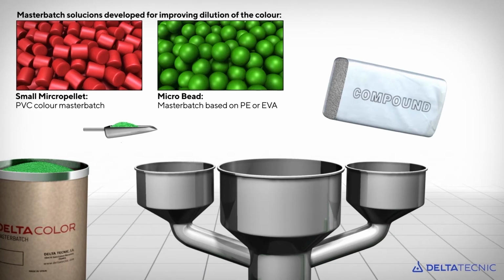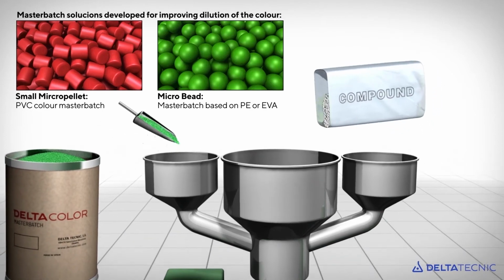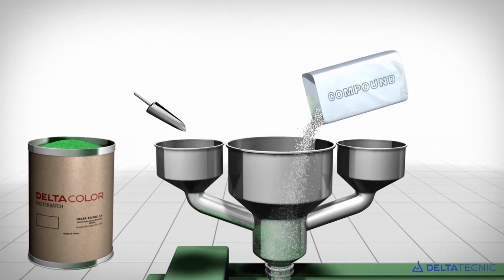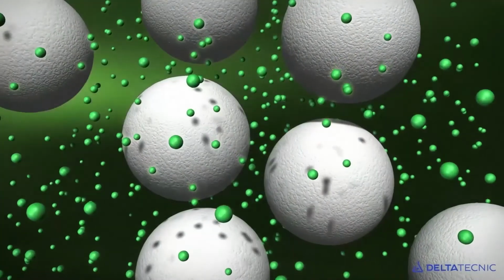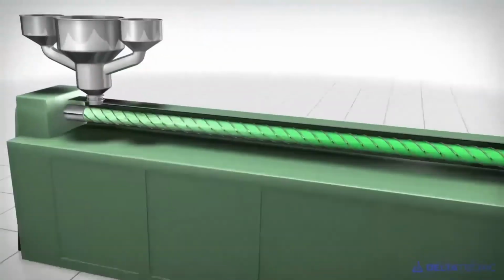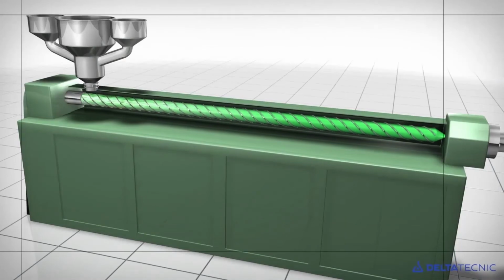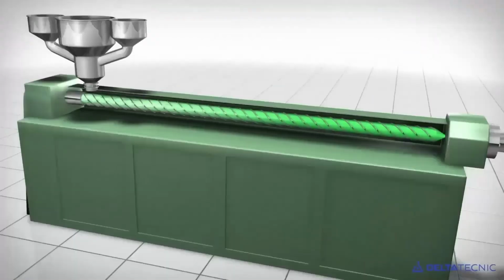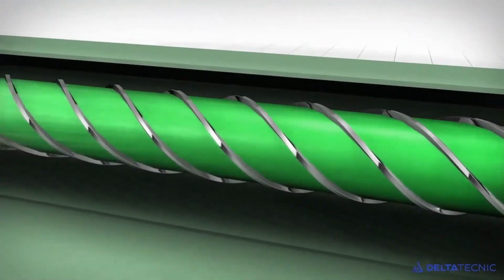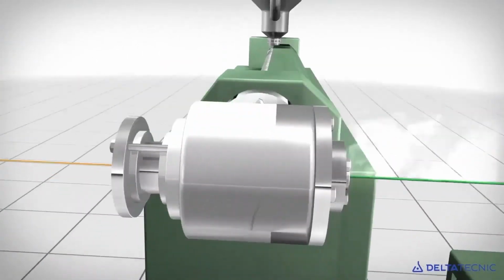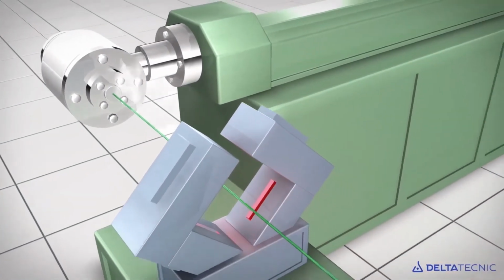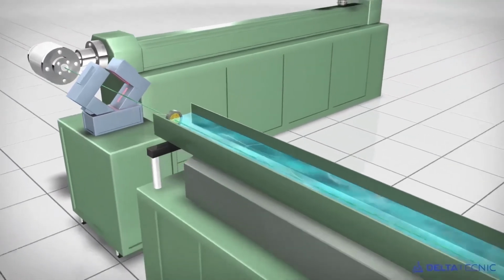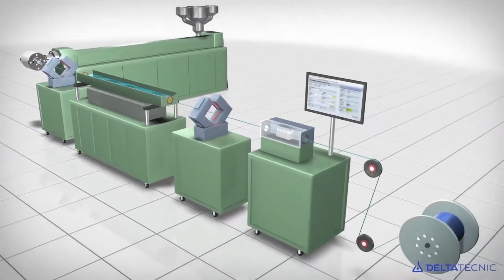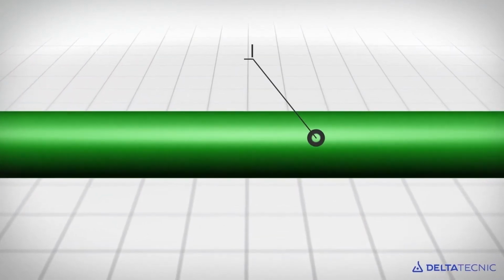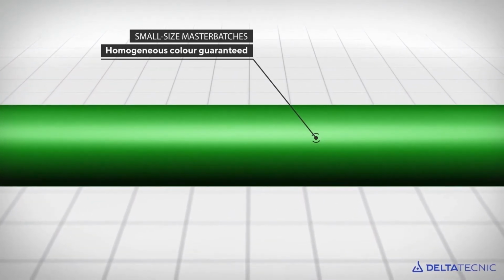Instead, if we go to smaller sized pellets, in this case with the microbead, you will see here in this 3D representation that the asymmetry between the color batches and the base compound batches is very big. Therefore, these much smaller pellets melt much quicker and therefore are able to produce a homogeneous surface, a homogeneous color surface on the cable. The process of dilution is the process of melting and incorporating the color into the compound, and that facilitates the color regularity of the outer sheath.